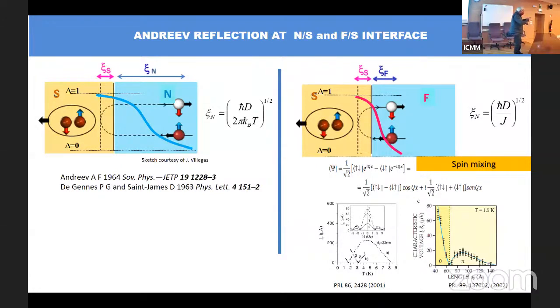The reason is that we measured the same conductance, placing the voltage contacts on top of the YBCO, which measures conductance across the interface, or placing the voltage contacts in the manganite, where you don't feel the interface in the voltage measurement. And we get exactly the same conductance. So this means that the transparency is very high.